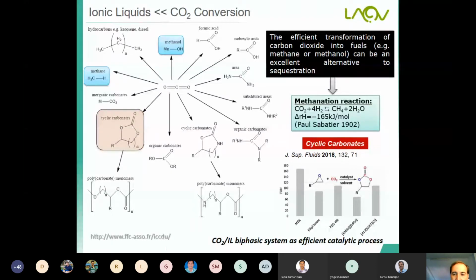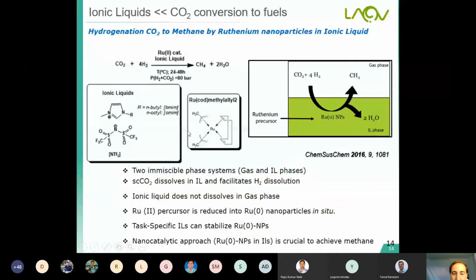in particular in the methanation reaction, that is the Sabatier reaction that you can see here, CO2 plus hydrogen to form methane and water. And some years ago, we proved that it's possible to do the hydrogenation of CO2 to methane using ruthenium nanoparticles in ionic liquid media. And how does this approach work? We are using a ruthenium precursor, in particular a ruthenium catalyst. This ruthenium methylallyl is a ruthenium(II) compound. It's commercially available, and we combine this with an ionic liquid, a hydrophobic ionic liquid.